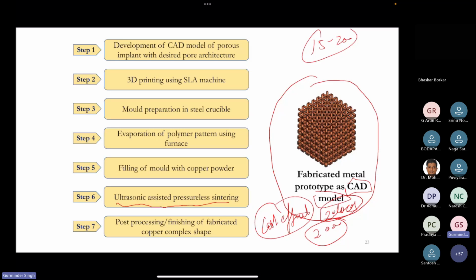But it is a little bit time consuming process. In SLM you can make it in 3 to 4 hours, but here you need one complete day. But you can make multiple parts, more than 10, 12 parts at one time, and you can save on that. Also it does not use extra material like in powder bed fusion and SLM, where you need a lot of raw material. Here you need raw material of exactly the volume of your product.